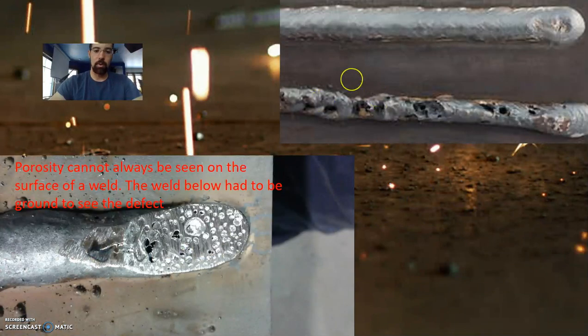This is caused usually by impurities on your weld surface. This is either going to be rust, oil, paint, anything like that is going to evaporate from the heat of your weld, create a gas, and it's going to get stuck in your weld as bubbles. Now you can see up here at the top of the right side, there's a nice weld bead running, and below is a weld that is just tore up. It's full of porosity. Looks like they ran it without any gas coverage. That's about the only way you can get a weld that bad.